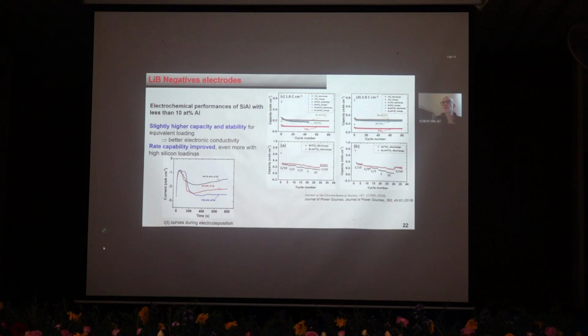And then we see on this graph right here the capacity versus the number of cycles, and the C represents the current used to charge or discharge the battery. 2C is a very high current, C over 10 is very low. And we see that when you add some aluminum, in red here, because the conductivity is much higher, we have a much better capacity.